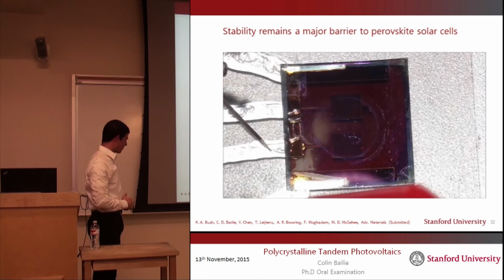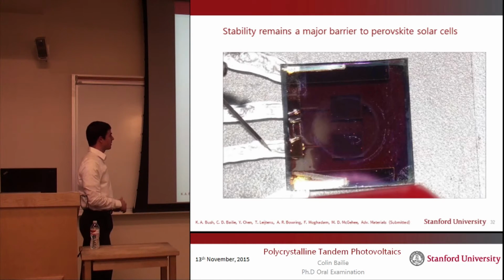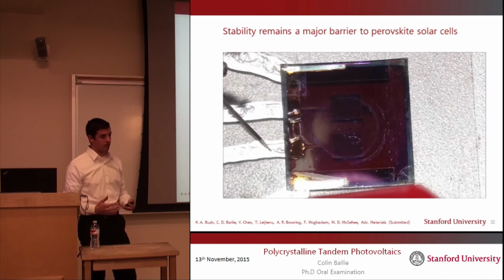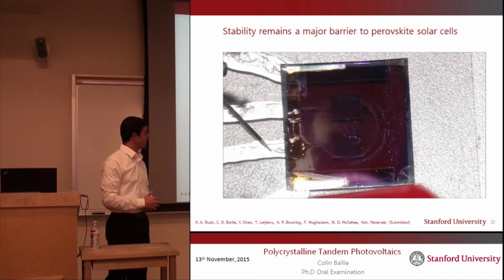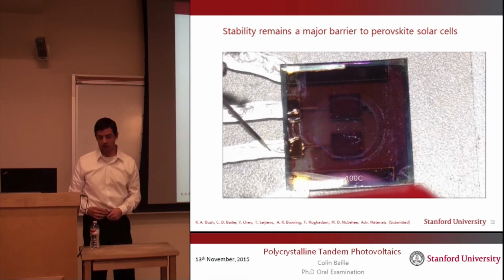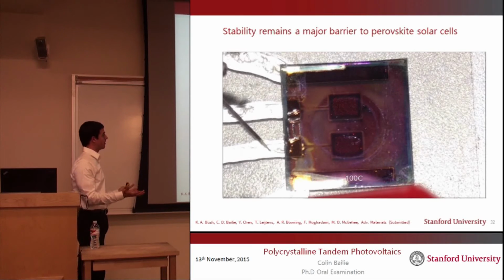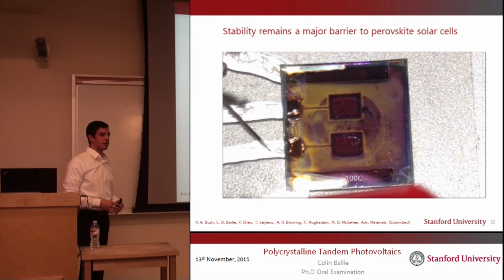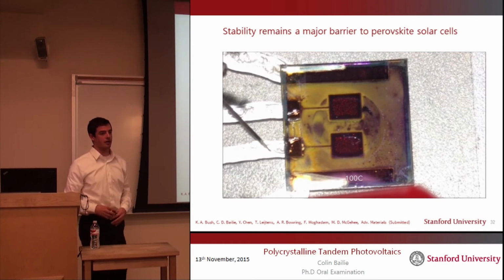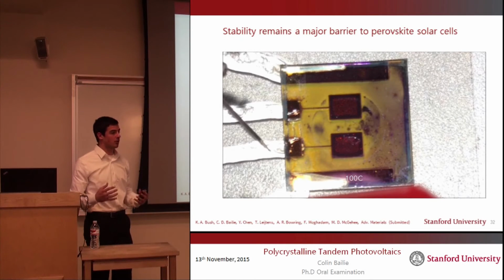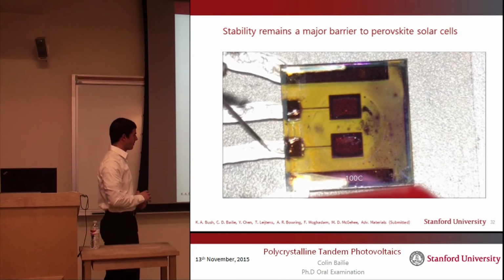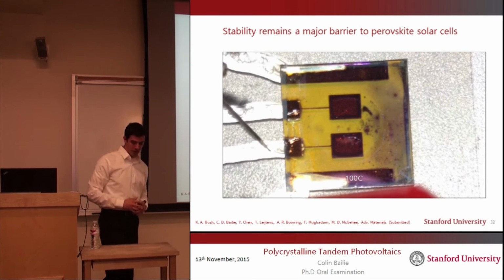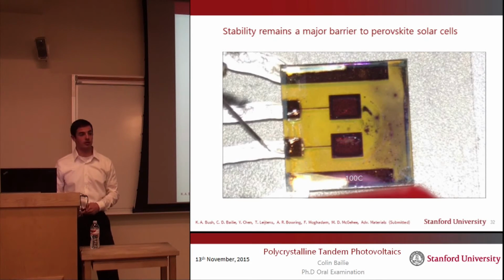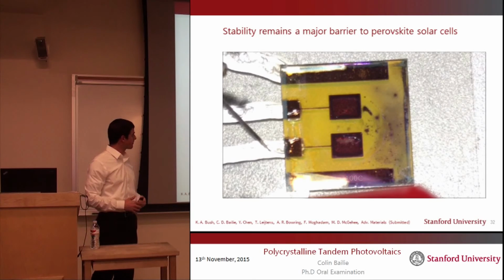So here's a short little video just to illustrate what this looks like. Now we've taken a metal electrode-based perovskite solar cell and put it on a hot plate. And the perovskite is brown when it's actually a perovskite, but as you heat it up, it turns yellow. And yellow is the color of lead iodide, meaning that there's no organic left in your system and you no longer have perovskite. So this is a good visual example of what this looks like when it happens.